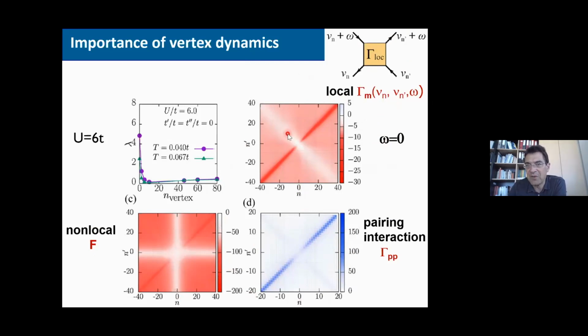And you see here the vertex is suppressed for small interactions, and the superconducting pairing interaction is suppressed for small interactions. In an RPA or recoupling approach, you would not have this suppression. You would have a constant vertex. Indeed, the constant background here is just minus U of the vertex. But if you take the minus U, you effectively do an RPA calculation, and you get a way too large lambda. You get Tcs that are an order of magnitude too high.